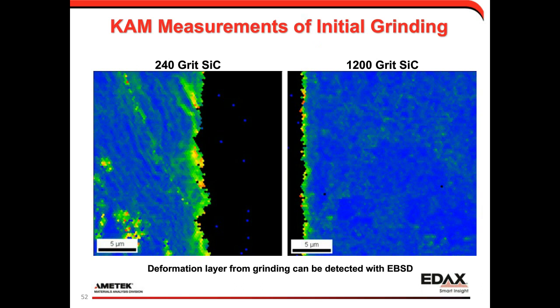And this is just kind of an interesting little slide. This is taking a surface, polishing it, and then cross-sectioning it, and then polishing the cross-section down to our final polish so that we can actually see the deformation layer that's introduced during different grinding steps. So the map on the left shows 240 grit silicon carbide. The polished surface is sort of on the middle right of that. And those warmer colors, the yellows and greens, show the deformation layer that's introduced with the 240 grit silicon carbide. We polish that down to 1200 grit.